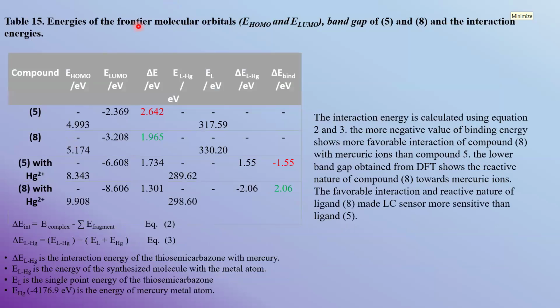And these are the calculations of energies, HOMO-LUMO, the band gaps, the energies of the ligand and mercury, and the binding energies. The interaction energy calculated using these two equations shows that the more negative value of binding energy is found for the interaction of compound 8 with mercury ion than compound 5. So the same type of result as we have seen in the case of UV and polarized microscopic results. The lower band gap obtained from DFT also shows that the compound is reactive in nature.